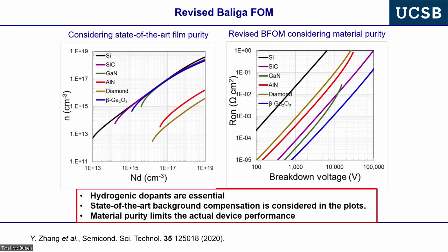And so what do these numbers mean in terms of purity? So if I have a purity level in the mid 10 to the 16s, how pure is that? That's a part per million, right? And a part per million for power electronics sucks, okay? Power electronics, you need to be closer to parts per billion, okay? Silicon carbide is ultra pure. Silicon carbide approaches towards parts per trillion, right? Okay, am I getting that right, Mike? Parts per billion, sorry, okay? Silicon towards parts per trillion, germanium, because of float zone growth, even purer, okay?